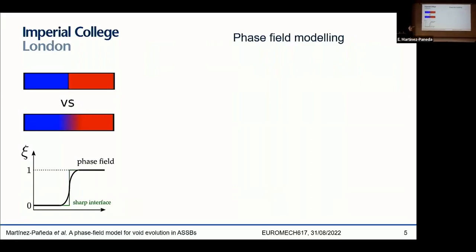So instead of describing the interface between two phases as a sharp, discontinuous interface, you can smear that interface over a finite domain and then use an auxiliary variable, this phase field variable, to interpolate between the two phases. This phase variable will take a distinct value in each of the phases: a value of 0 in the blue phase, that is the voided region, for example, and a value of 1 in the red phase, that could be the solid lithium metal phase. And then it will vary smoothly in between. Just by defining a differential equation for the evolution of this phase field, you're able to capture complex interfacial morphology problems.